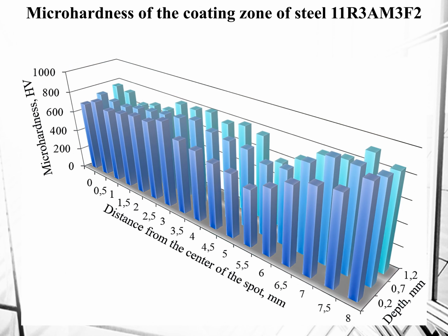The hardness of the 11R3AM3F2 steel sheets before they were welded in the initial state was 57.08 HRC. In the zone of thermal influence, tempering, after the electrocontact resistance welding it decreased to 51.4 HRC, while inside the welding spot, the rehardening zone, hardness increased to 64.0 HRC. Similar data were obtained when analyzing the results of measurement using the micro-Vickers method. At the welding spot the maximum average hardness value is 904 HV, in the tempering zone 595.6 HV, in the zone with the initial structure 804 HV.